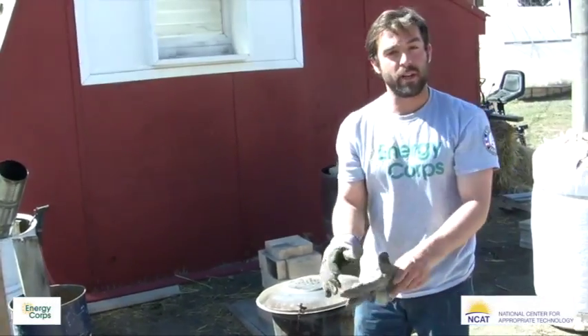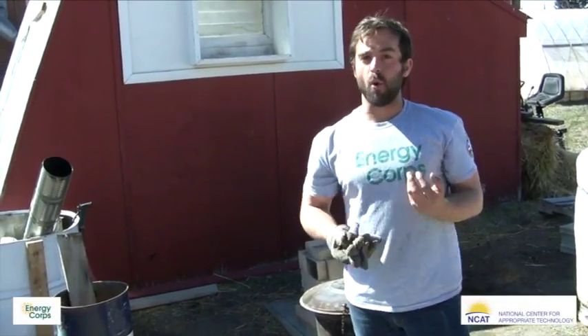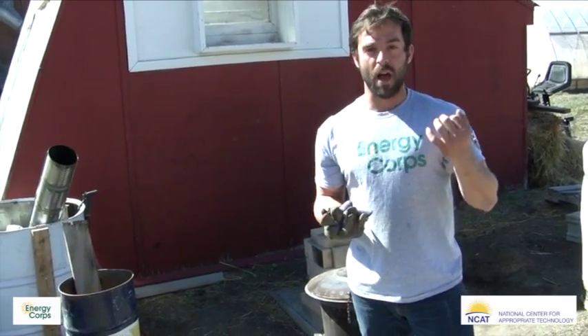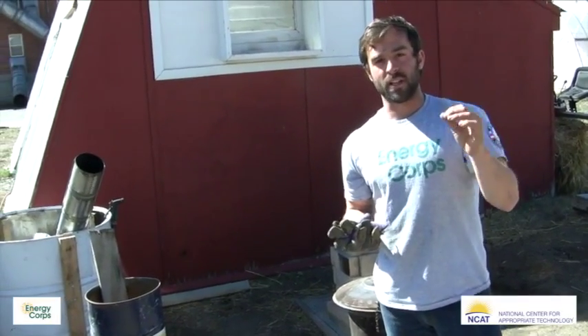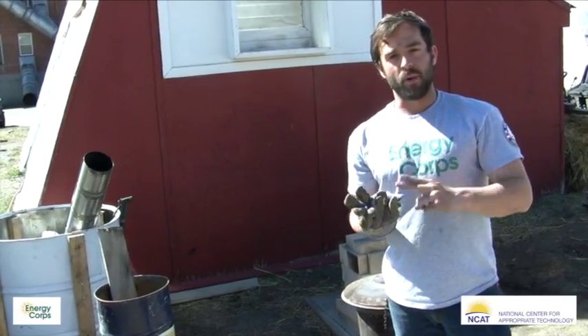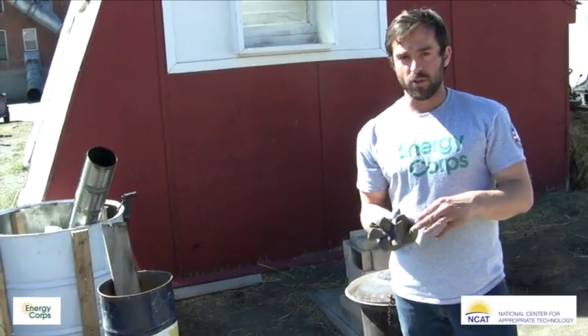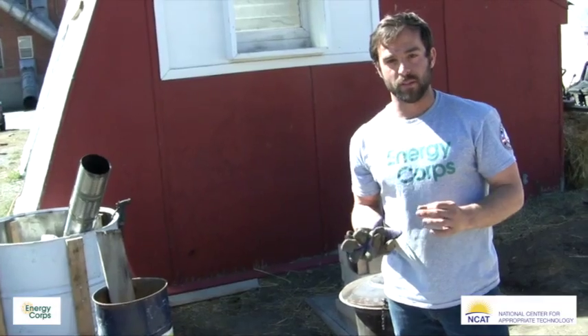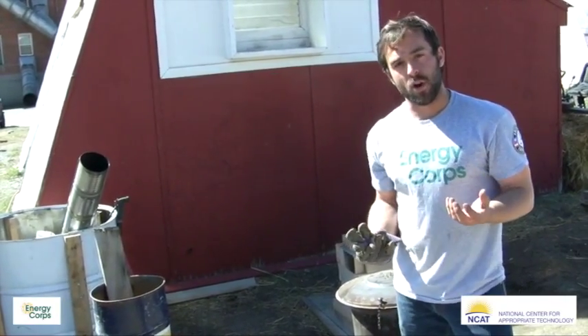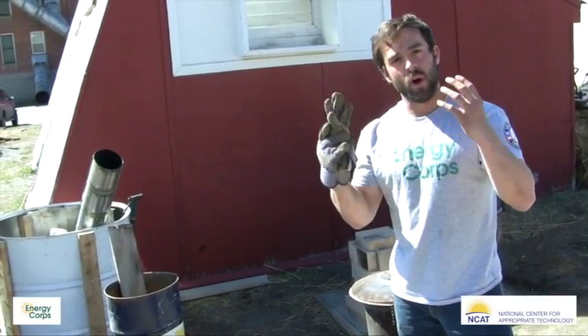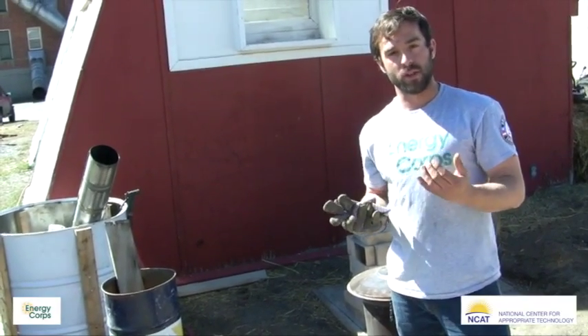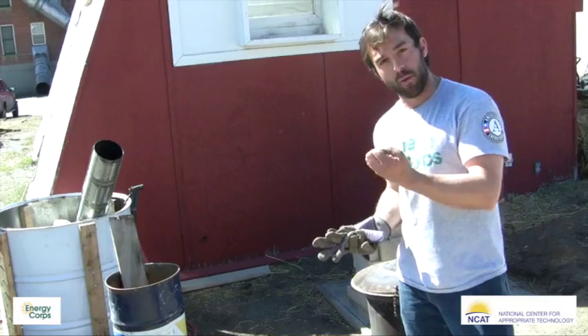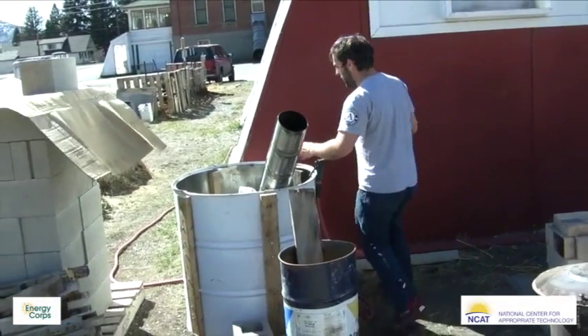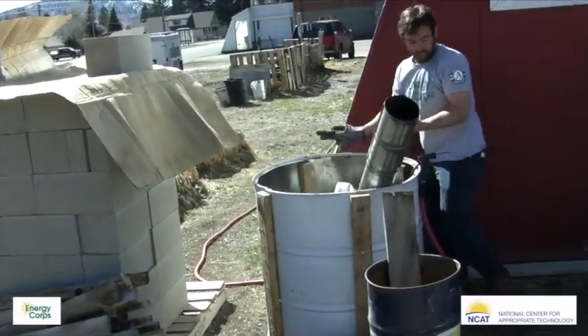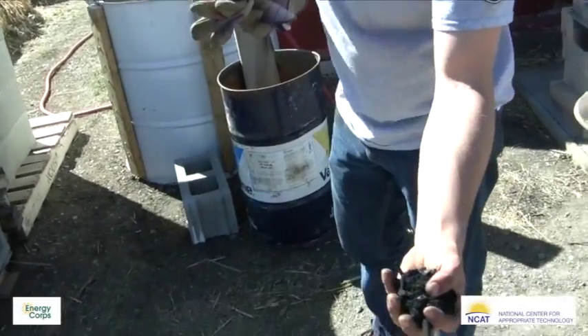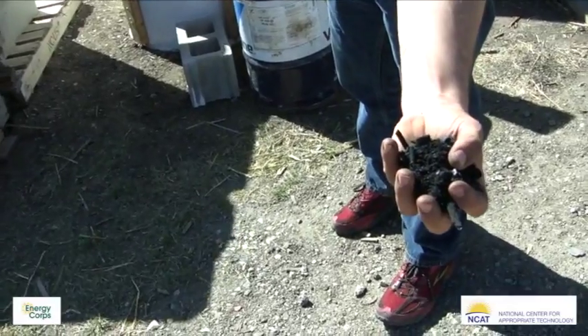The reason why you want to pulverize the material is because biochar is very porous, and that's its main attribute. So the pores have several different functions, like I talked about before. It aerates the soil, it breaks up clay, absorbs water, absorbs nutrients, and creates kind of a luxurious home for those microorganisms. So to be most effective, you want the biochar to be crushed up, and you want to increase the surface area and expose as many of those pores as possible. So you want to take this material and crush it up and pulverize it. And so by the end of crushing it up, you're going to end up with something like this. Should be a very dusty material. And at this point, this char is ready to be added to the soil.